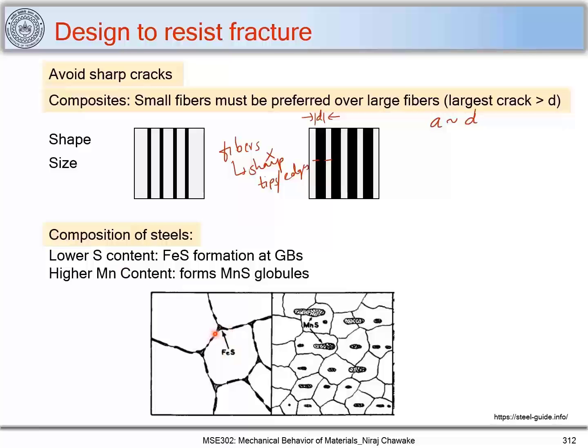or sharp precipitates which form at these grain boundaries, and thus this FeS makes these grain boundaries susceptible to crack propagation, and thus it decreases the fracture toughness of a material. So any phase at the grain boundaries which is brittle, this FeS is also brittle, increases the stress concentration and thus makes this material susceptible to crack propagation. This FeS acts as a location for crack nucleation and propagation itself. So if you have more amount of sulfur, it leads to more amount of iron sulfide at the grain boundaries.